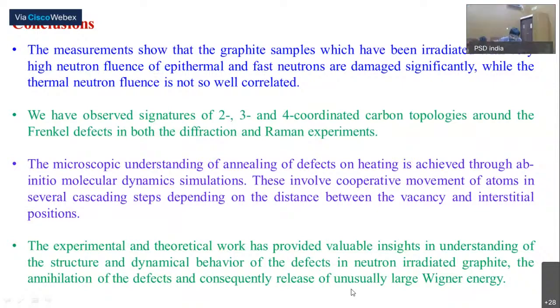All these samples were irradiated in our reactor for 20 years, because the flux was 10 to the power 13 and the total fluence is 10 to the power 21. If I multiply flux with time, our reactor was operating for about 20 years, so multiplying neutrons per centimeter square per second and time, I get a total neutron fluence of 10 to the power 21. Okay, so these were quite valuable samples then, because they have such a lot.